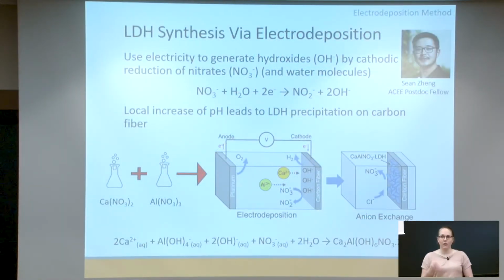And then what Sean's done is done an anion exchange, whereby it's preferential for chloride ions to exchange for the nitrate ions, and therefore you can end up with calcium aluminium chloride layered double hydroxide.